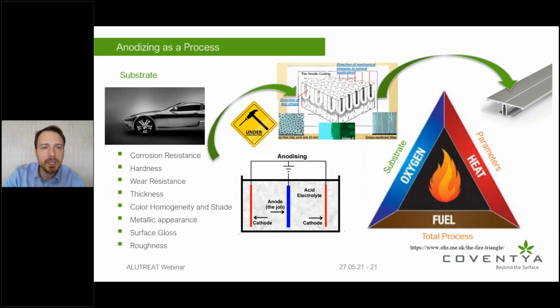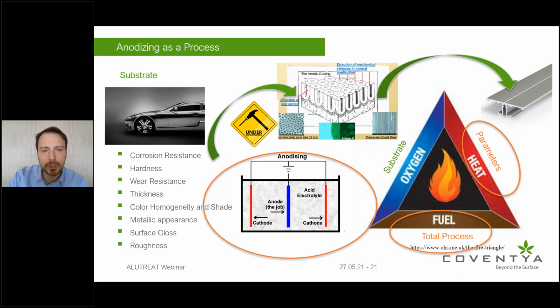So therefore, we give a very high importance to how these layers or how these pores are structured or constructed, as you can see here. And in order for us to be able to visualize this, I like to use this analogy with the fire triangle, where you have your substrate and it is limited. So whatever your substrate doesn't have or has too much of, you will have to compensate throughout your process with the parameters you use, and utilize your process in order to construct the right surface, the right oxide structure that you need for your application with the right desired properties.